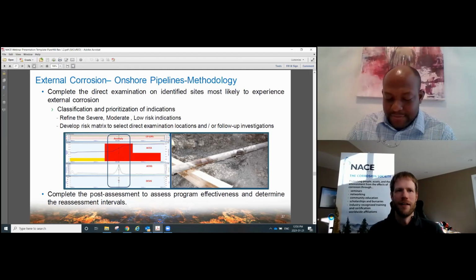Yes, Brett, I think I've received this question more than 20 times at every NACE conference, and I'm going to address it based on industry best practice. When the pipe is buried, coated, and cathodically protected, has a very high dielectric shielding coating, and the pipeline is new, as a rule of thumb less than 20 years, inline inspection is the best tool for assessing that pipeline segment. The reason is that because it's high dielectric, it shields: water gets in, the CP cannot get to the pipe, and you have external corrosion. You can even do an overline survey that shows the pipe is protected, but you're having a very big problem. Inline inspection is the best tool for that specific instance.